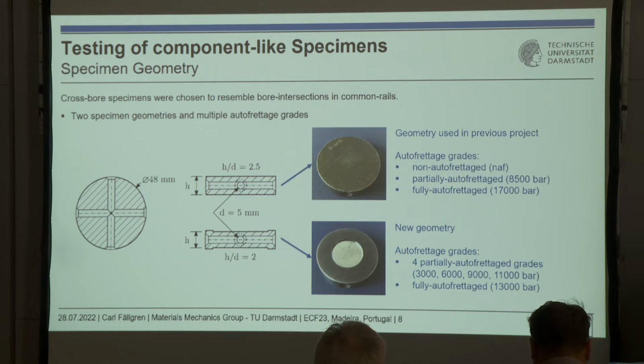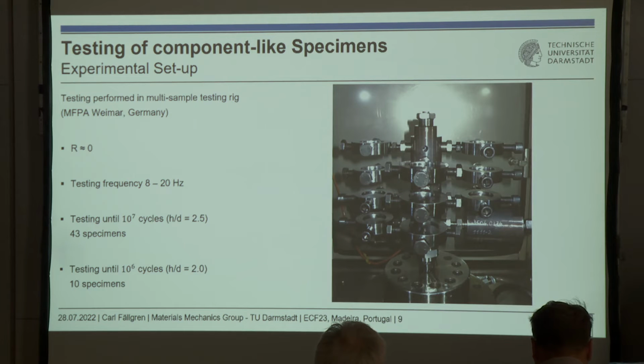The testing was actually performed at our partner research institute in Weimar, Germany, at the MFPA. They used a multi-sample testing rig. Our load ratio was approximately 0, but due to experimental conditions, the lowest pressure was always at 5 bars.